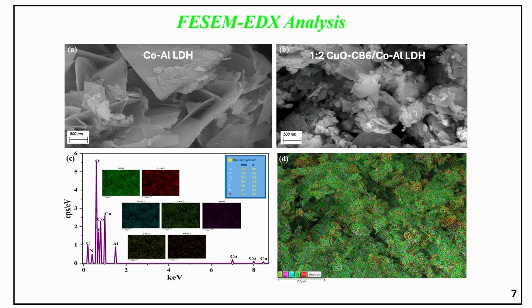Next, coming to FESEM EDX analysis. Here, the structural morphology and elemental composition of the materials, cobalt aluminum LDH and 1:2 nanocomposites were analyzed using this FESEM EDX analysis. The cobalt aluminum LDH exhibited a smooth nanosheet surface morphology. The 1:2 nanocomposite was confirmed to be formed by the presence of spherical shaped CuO-CB6 nanoparticles situated between the layers of cobalt aluminum LDH nanosheets. Elemental mapping from the EDX analysis showed a uniform distribution of all the elements including copper, oxygen, cobalt, aluminum, nitrogen and carbon within the nanocomposite. Therefore, this analysis confirms the CuO-CB6 is successfully positioned within the cobalt aluminum LDH layers.